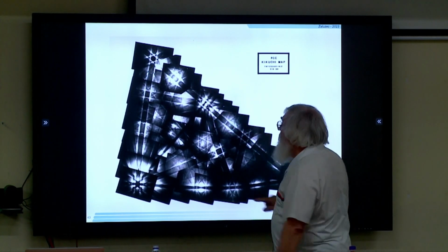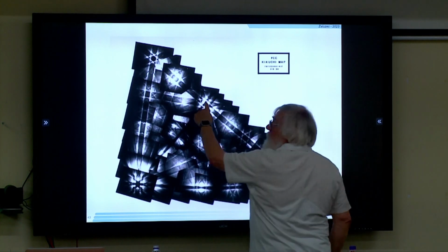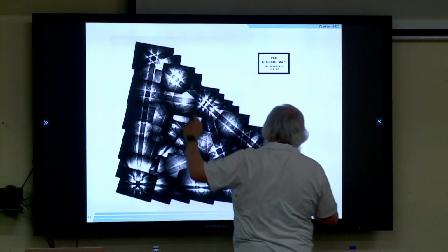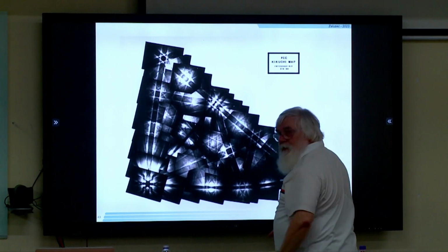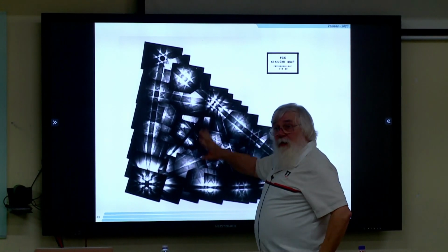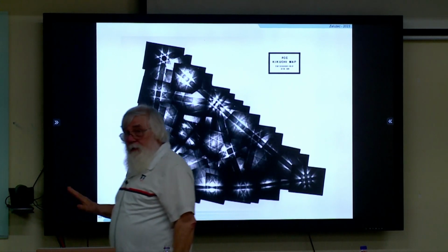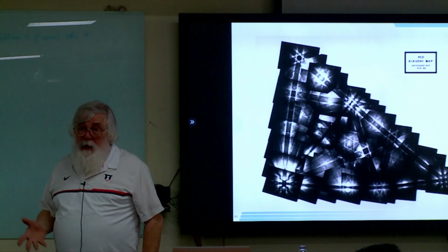Similarly, we can go along here. From there to there, the first major one is 112. So that's 111 plus 011, 112, 113, 114. We can do vector math in here. Very simple way of indexing your pattern. More importantly, it's a roadmap of your crystal.